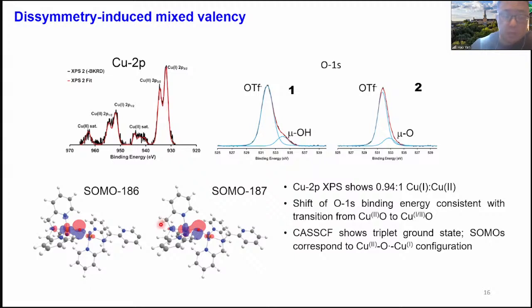This is backed up by CAS-SCF calculation: the copper in the 6-coordinated field is still copper-2, the 5-coordinated field is still copper-2, whereas the other copper that sits in a 4-coordinated system is copper-1. That implies the bridging oxygen should carry some radical characteristics, so it's probably a mixture between oxo and oxyl.